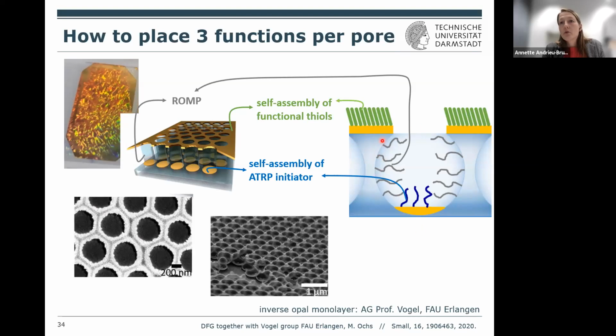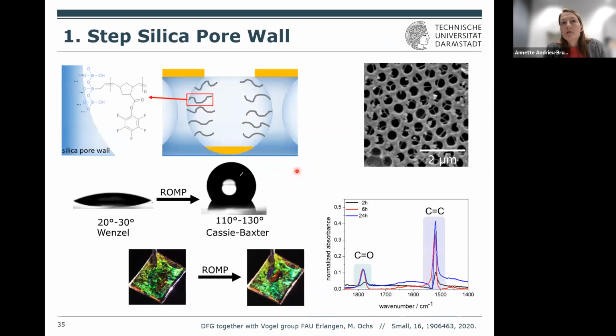So we had these inverse opal monolayers, and the group of Nikolaus Vogel is able to just functionalize them with gold at the outer surface, with gold at the bottom of the pore. In addition, of course, now you have nanoscopic metal layers that are plasmonic, and you can think about using this plasmonic response for sensing. This is what they did in the project. And then ask the question how to get 3 different functions. So one on the outer gold surface, one on the silica pore wall, and one on the bottom gold layer. And we did this by combining orthogonal surface chemistry and wetability changes.